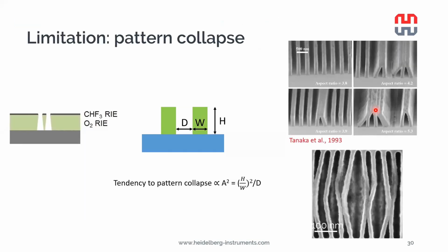The limitation of the high resolution liftoff is the pattern collapse. As you can imagine, if you have a very thick PMMA film and very high resolution pattern, then the aspect ratio of your structures, that is the height divided by the width, becomes higher, and the tendency to pattern collapse is directly proportional to the square of the aspect ratio. And here we can see in these images where the aspect ratio is slowly increasing, and we can also see the amount of pattern collapse becoming more and more dominant. And from the top, the structure looks like this, and this is not very useful anymore for the liftoff.